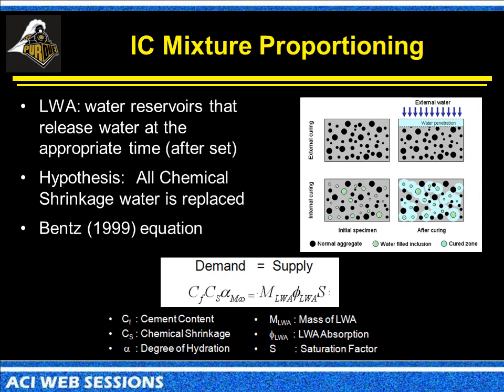In Dale Bentz's group, they developed an equation which really equates the supply and the demand that are needed in the system. So we can do a simple calculation that tells us how much internal curing water we need to supply to overcome the effects of chemical shrinkage. We basically calculate how much cement we've got in the system, the chemical shrinkage of that cement, and the degree of hydration that that cement is going to undergo. Now remember, if we start adding fly ash to the system, we've got to add some additional terms in here where we essentially say we've got cement, the chemical shrinkage of that cement, we've got the fly ash, the chemical shrinkage of that fly ash.